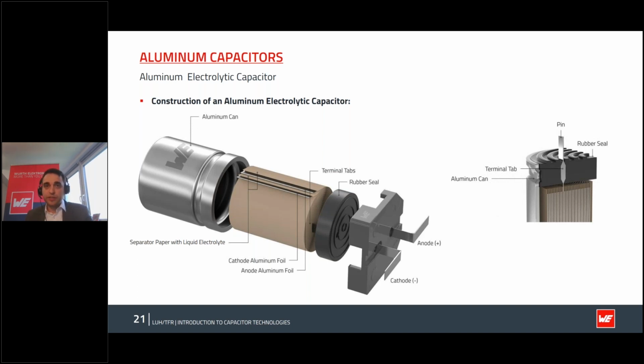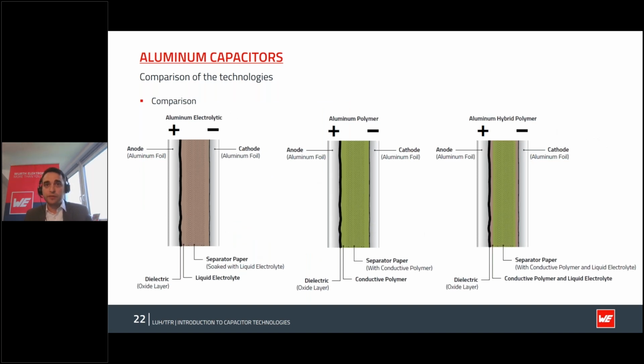So you can see the internal structure here. On the left, you can see the standard aluminum electrolyte part. You have the aluminum, then you have the aluminum oxide layer, which is defining the voltage range here. And then you have the paper here, which is soaked for this case in a liquid electrolyte. And then on the other hand, you have the cathode foil. You see over time, this aluminum oxide layer can decrease in thickness, which would increase the capacitance, but decrease the voltage range. But as long as there's a little bit of water in the electrolyte here and you apply voltage, you can have a certain self-healing ability here for this layer.